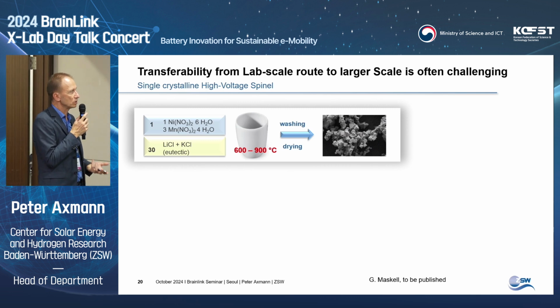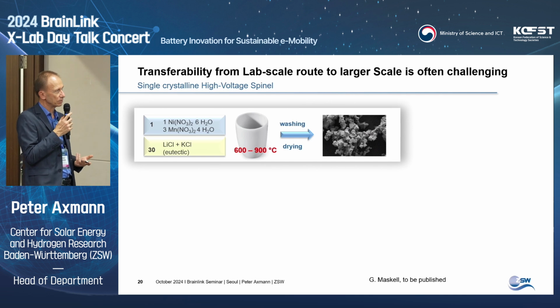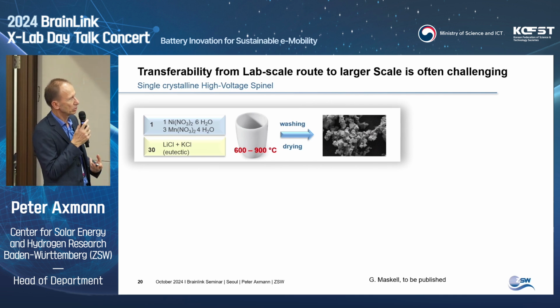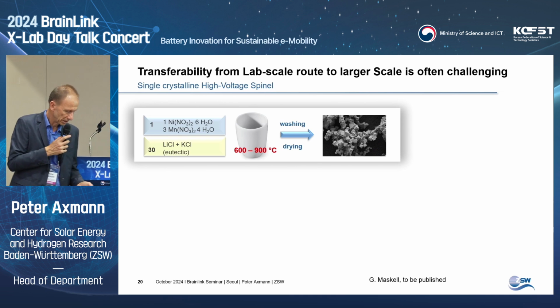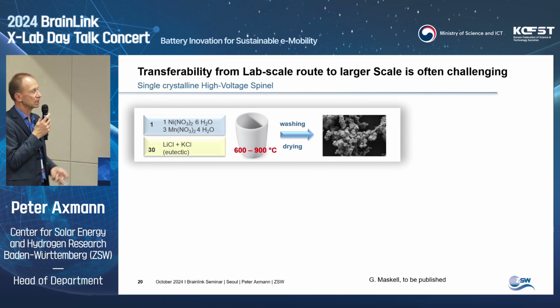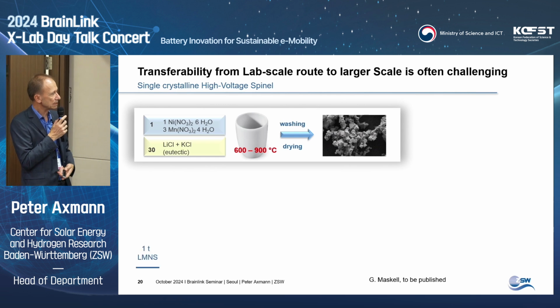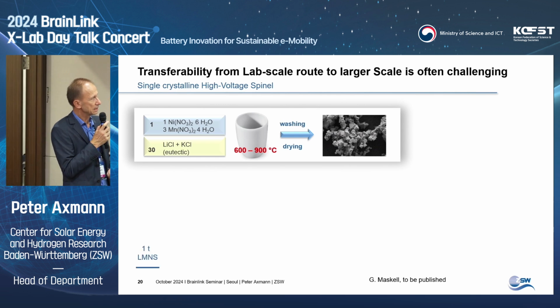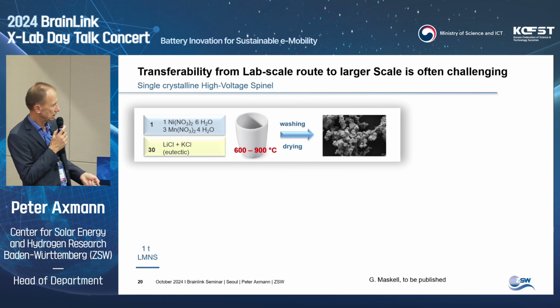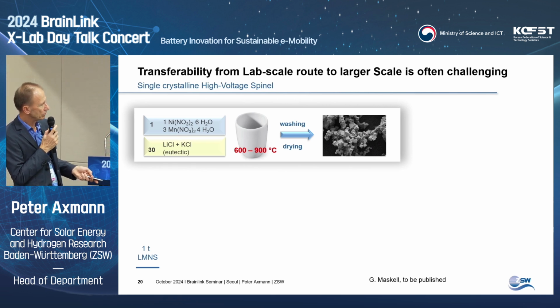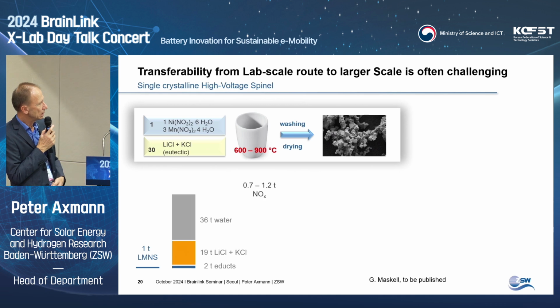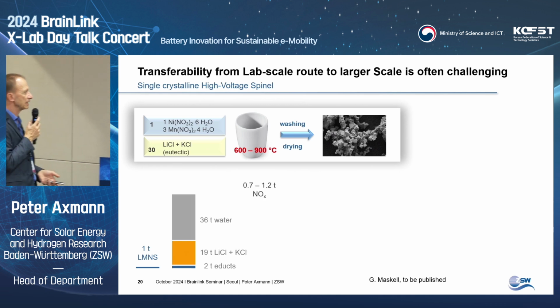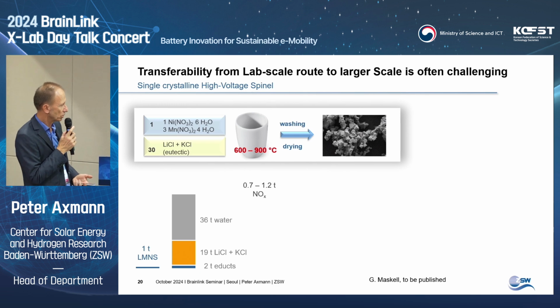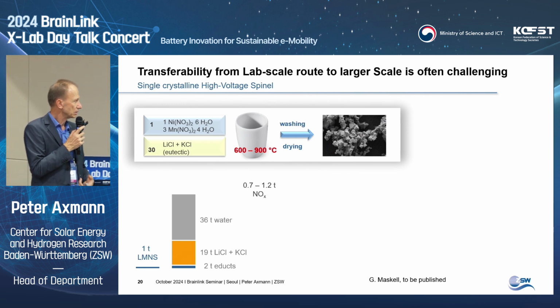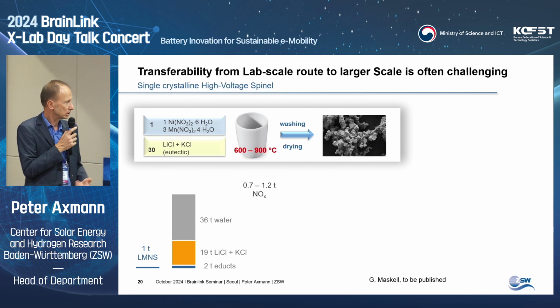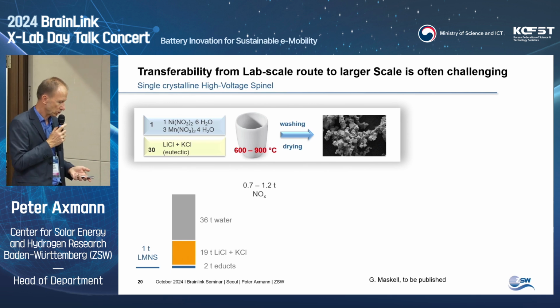So these routes are very good to get general information about the scientific background. How does this material work? What is needed to improve a material? But if we then want to make this material in a larger amount to make real cells, we end up, let's say, that it's not possible. Just taking a calculation, 1 ton of high voltage spinel made after this recipe would need 2 tons of educts, it would need 19 tons of lithium chloride and potassium chloride, and later it would need a minimum of 36 tons of water to wash out the lithium chloride and potassium chloride as well.